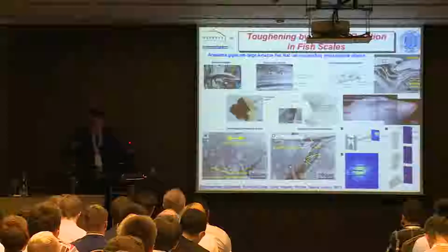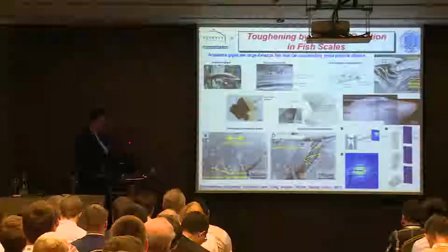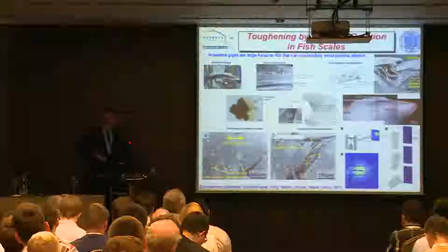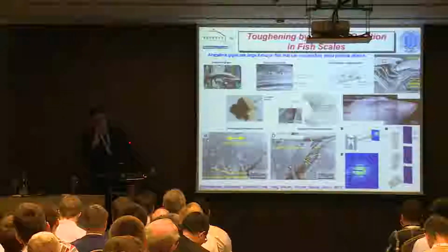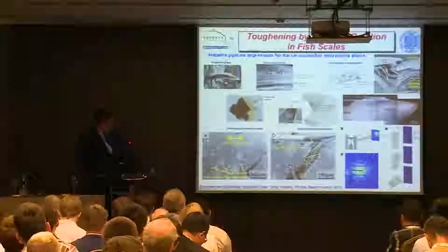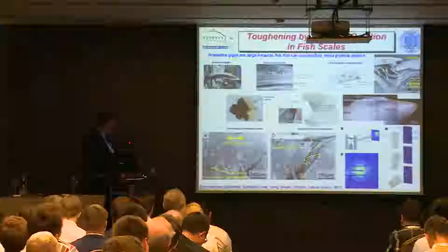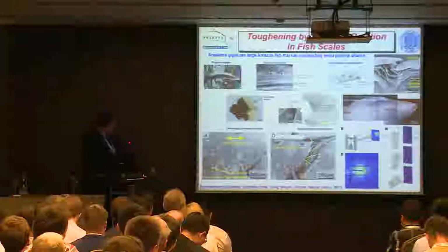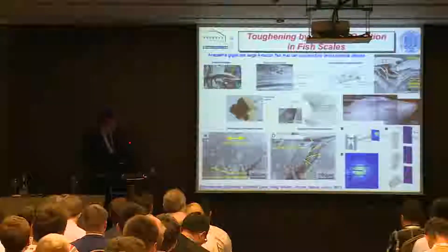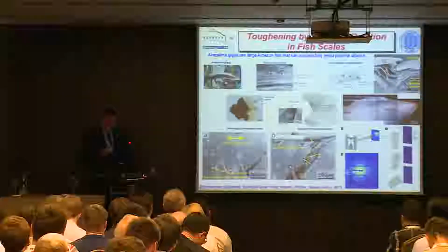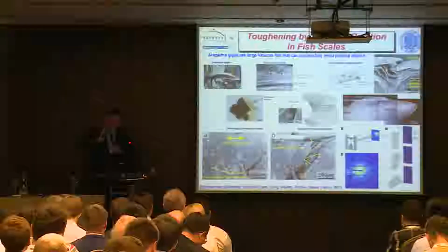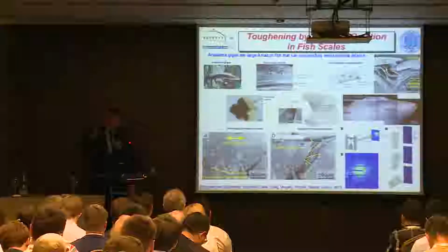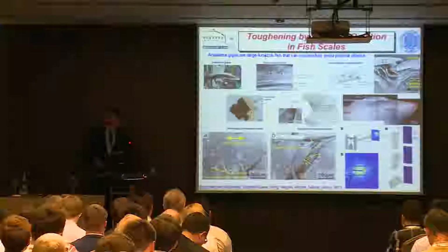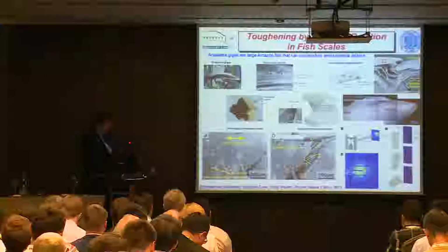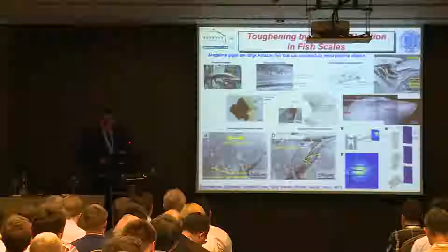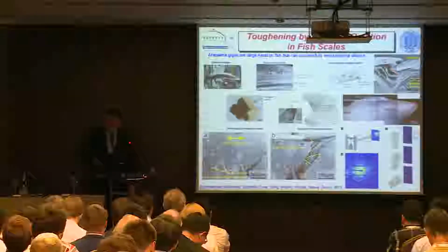And how does that work? Again, we put this in the synchrotron. And what we find is that the collagen will simply rotate to carry more of the load. It's a beautiful mechanism, and we can watch this in real time. These structures tend to be what's called Bouligand structures. They're like a spiral staircase, and they will simply rotate. These are the ones that are closer to the tensile axis, and they'll carry more of the load. And there's some fish that have double Bouligand structures, which are even more complicated. Very, very interesting.